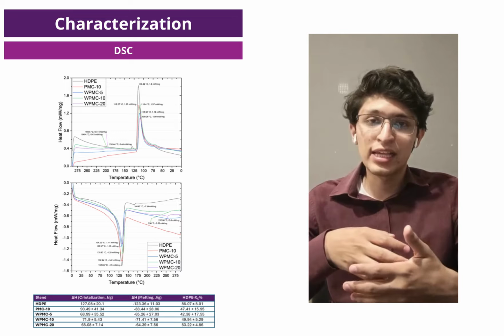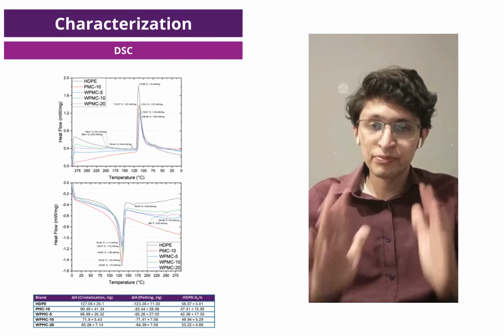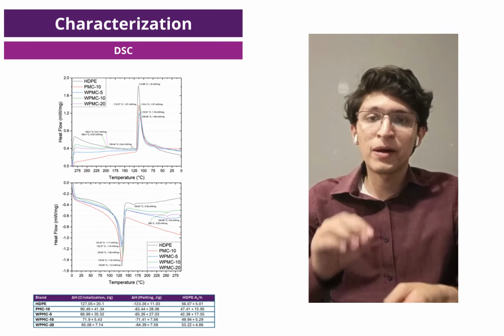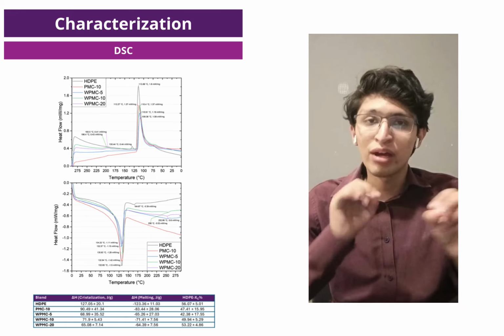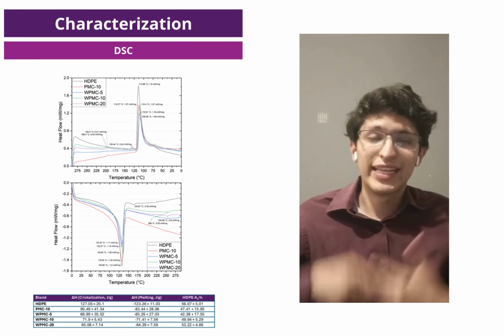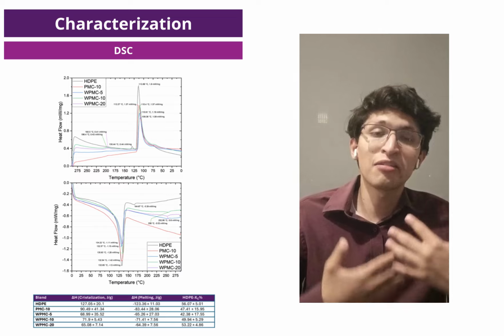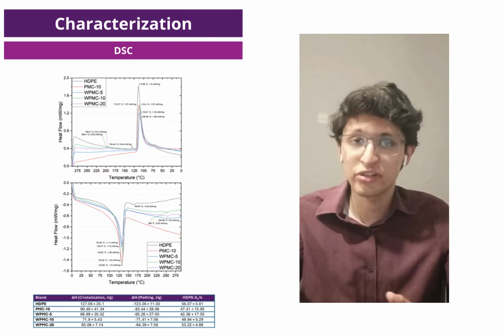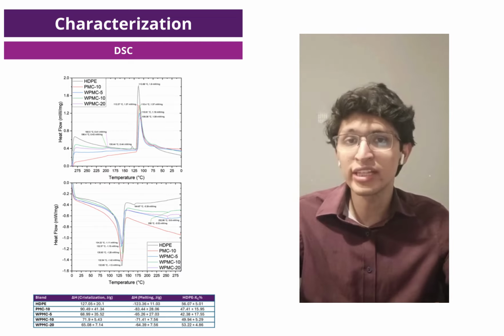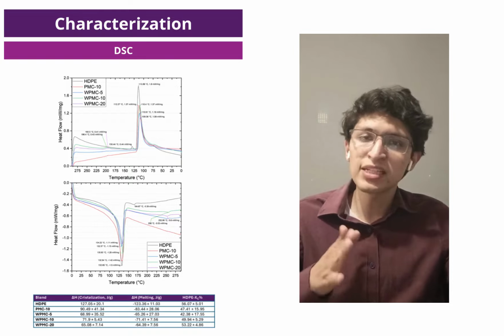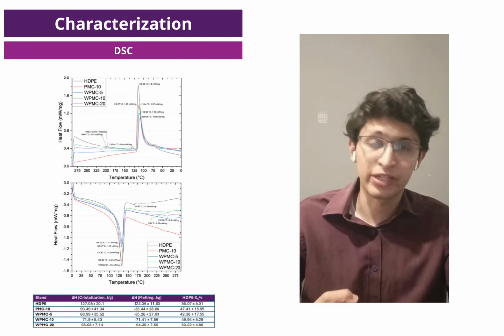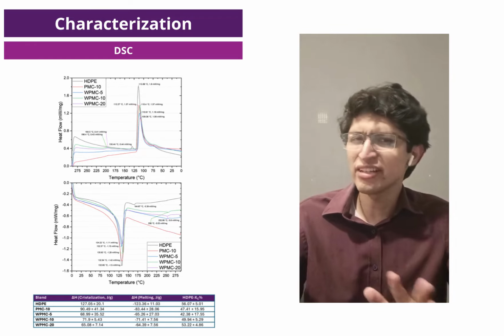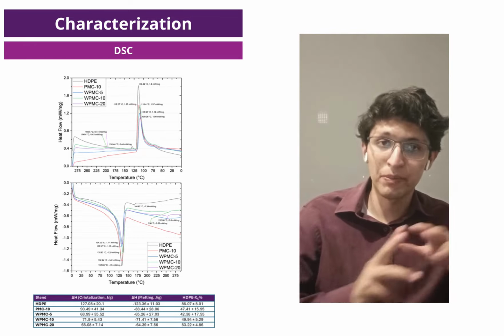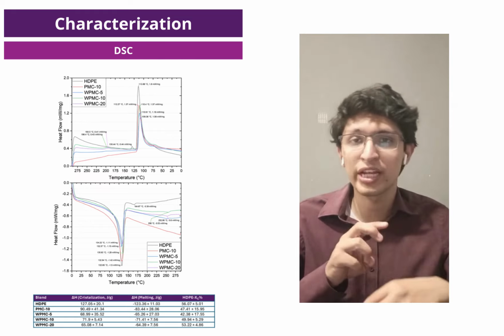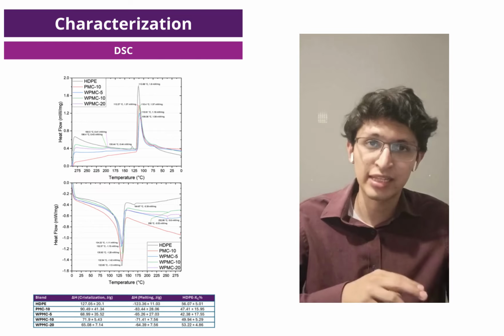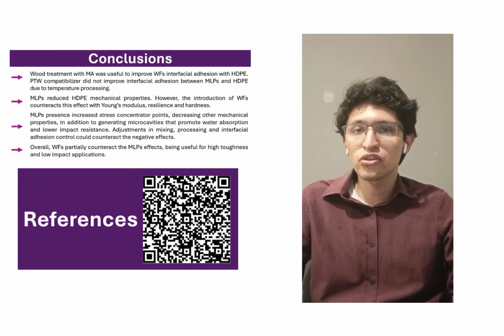On the other hand, the slight changes on the melting temperature are an indicator of a reorganization of the crystal structure and the lamellar thickness of the material. Now, talking about the crystallization percentage, we can observe two opposite behaviors competing with each other. The first one is the polymer chain restriction that reduces crystallinity. An opposite effect to that is the nucleation effect that the calcium carbonate, the multilayer plastics, and at a certain degree the wood fibers have on the polymeric matrix, being this more pronounced at higher multilayer plastic percentages, such as at 20%. Let's end this presentation with our conclusions.